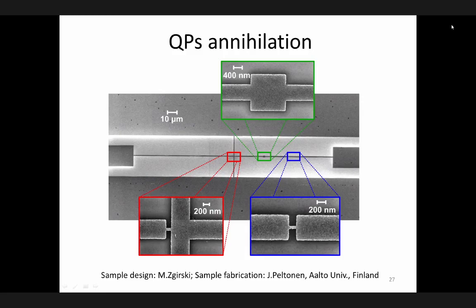So when you have, say, electron-phonon relaxation time at 300 milli-K, which is on the order of 5 microseconds, then when you apply a perpendicular field of 300 millitesla, it will be maybe a factor of 2 or 3 faster. So these are studies that you can also do. But in principle, with perpendicular field, everything is suppressed much faster.